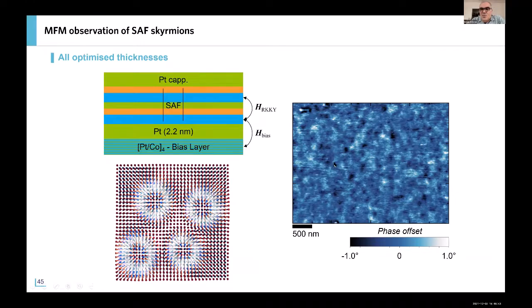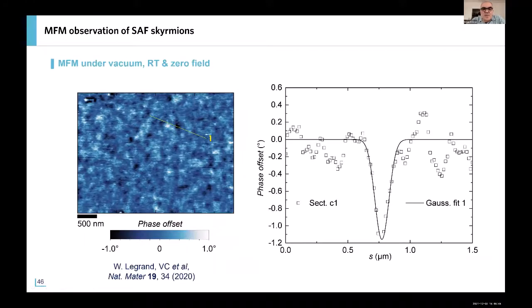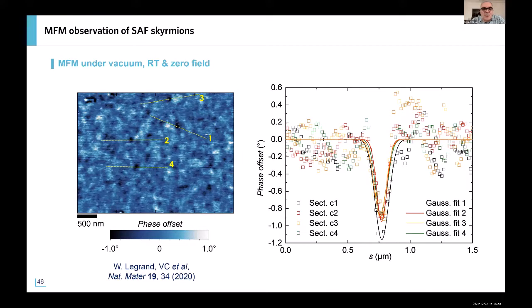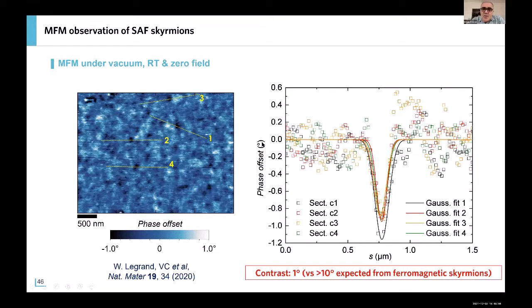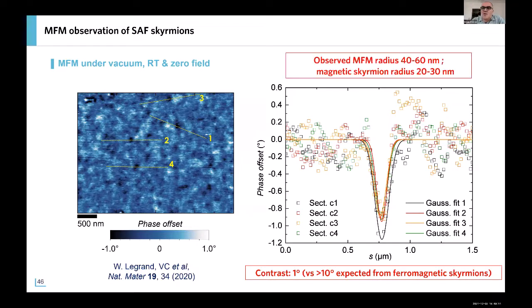Maybe it's hard to see, but if you make a line section across different black dots, you do see a signal whose amplitude, the contrast, is about 1 degree, whereas when we make the same images on the ferromagnetic skyrmions, we can measure 10 degrees. So this is already a signature that we do image antiferromagnetic skyrmions, very weakly magnetic skyrmions.